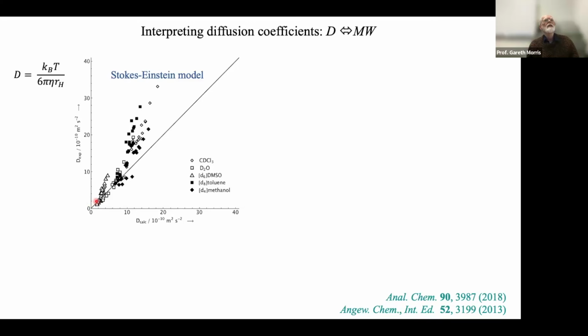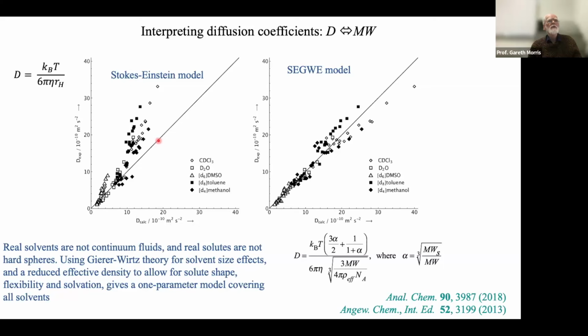molecules. So what's going on here is that the Stokes approximation that molecules are balls moving in a continuum solvent isn't really valid. We have to consider the actual sizes of the solvent molecules, in particular the ratio of the solute hydrodynamic radius to the solvent hydrodynamic radius. But if we do that, then we can actually get a reasonable fit, an analytical relationship, that means that we can estimate diffusion coefficients to within 10 or 20%. It's not great, and that corresponds to an uncertainty of up to 50% in molecular weight, but it's still an awful lot better than the Stokes-Einstein model.